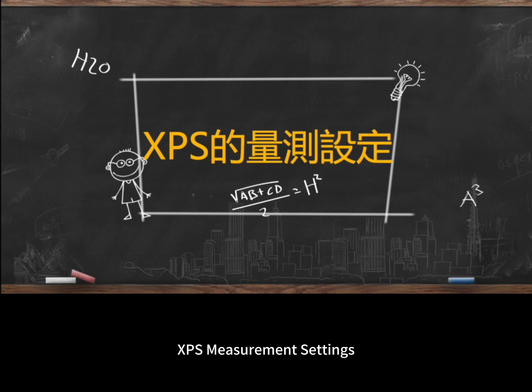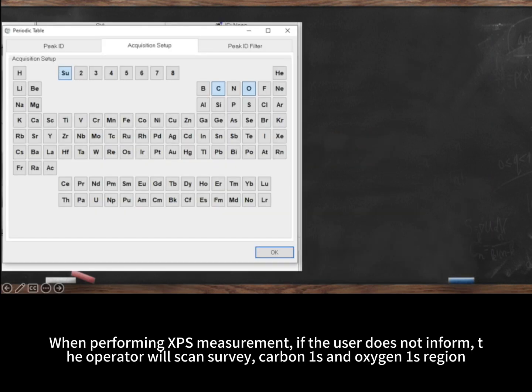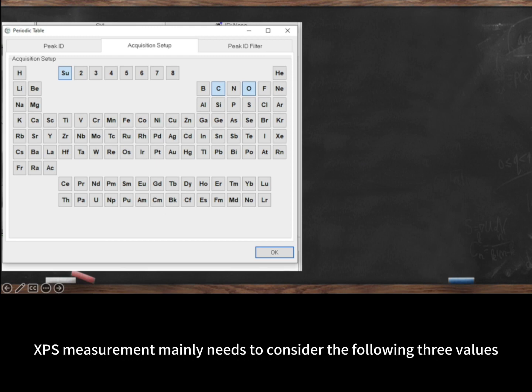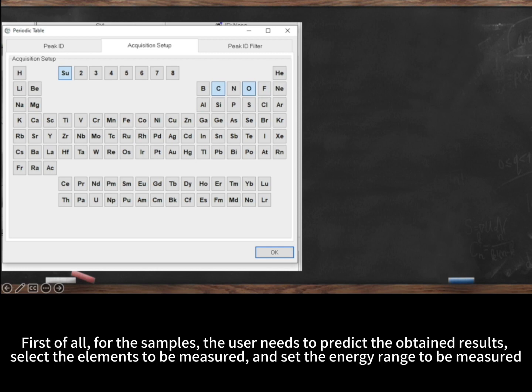XPS measurement setup. When performing XPS measurement, if the user does not inform, the operator will scan the survey, carbon 1s and oxygen 1s regions. XPS measurement mainly needs to consider the following three values. First of all, for the samples, the user needs to predict the obtained results, select the elements to be measured, and set the energy range to be measured.